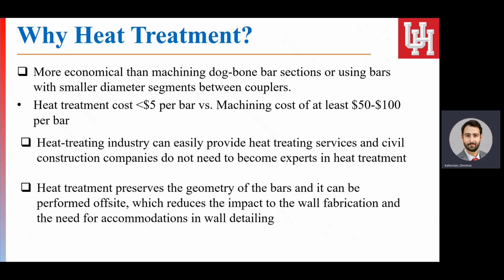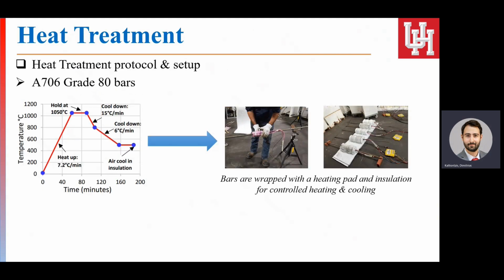Another benefit of using this approach is that the heat treatment is going to preserve the geometry of the bar and can be performed offsite, which reduces the impact to the wall fabrication and the need for accommodation in wall detailing, as would be the case, for example, with couplers, where we locally increase the diameter of the bar where the couplers are located, or where the bar diameter is reduced through machining, which also needs some accommodation in the wall detailing. All of this will not be needed in the case of heat treatment, as the geometry of the bar will remain the same.